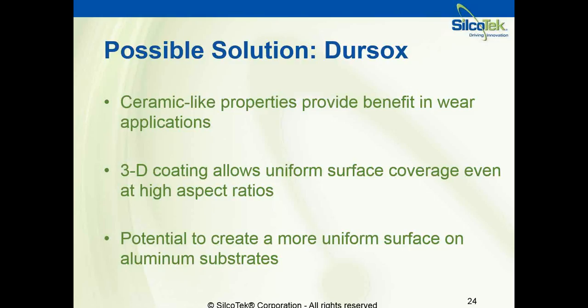Yttria and other ceramics are common solutions with semiconductor. They rely on line of sight or other complicated deposition methods and special fixturing to even get a uniform and conformal layer on the substrate. Aluminum, another common solution, is a very difficult surface to control. With our coatings, you have the opportunity for a very reproducible, very repeatable deposition process that will result in an extremely thin coating that you can bend and flex with parts as needed. For example, showerhead components are easily coated, as are bellows, and the coating will not suffer as those parts move as required by the application.